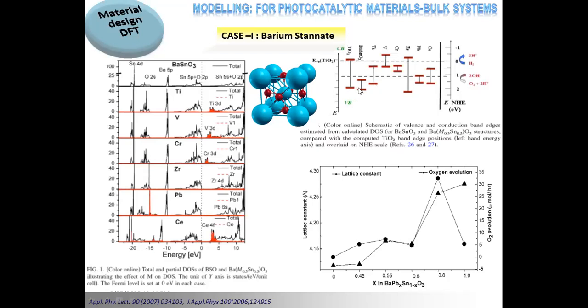Barium tin oxide, again, there are certain limitations with respect to the software sometimes, and the functionality of the software is also based on assumptions which are related to the final outcome. But nonetheless, if we know a particular drawback, then based on that, we can relatively look at the computational result. What we see here, when you dope titanium, vanadium, chromium, zirconium, these are the possibilities. It shows that the zirconium doped one can be used as a photocatalyst, but its band gap is too large, more than 4. It is not actually a good idea.